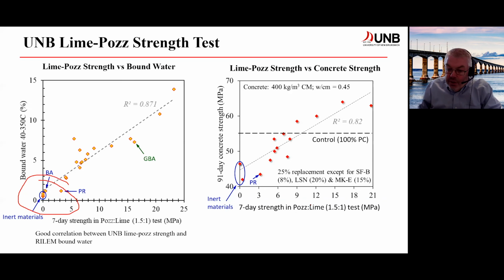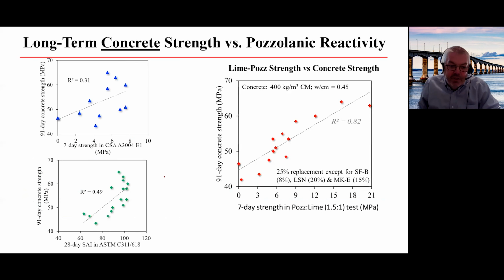And we also get a very good correlation between the 7-day strength of the pozzolan lime mortars and the 91-day strength of concrete produced using the same materials. And this is important, that the reactivity in the test is reflected by its performance in concrete. Although I have to say the concrete strength or mortar strength is probably not the best assessment of pozzolans. Pozzolans can produce great benefits to concrete without necessarily benefiting the strength. I think most of us who work with pozzolans will know you can reduce permeability without really increasing strength. And so you can get benefits without it necessarily being shown in terms of strength.